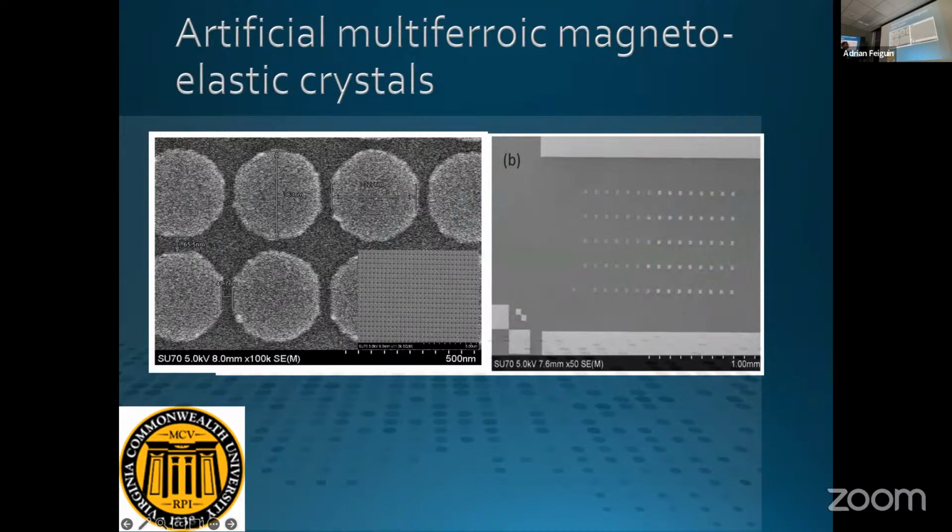All right, so multiferroic, because cobalt is a magnetostrictive material, and that's important. You cannot use a non-magnetostrictive ferromagnet. You have to use a magnetostrictive ferromagnet because you need magneto-elastic coupling. Magnetostrictive ferromagnets are subject to the Villari effect, which is the inverse magnetostrictive effect, so that if you apply strain on them, you will actually rotate the magnetization. And if you apply periodic strain, the magnetization will go back and forth. In other words, the magnetization will precess. So you'll have precessional motion in magnetization.